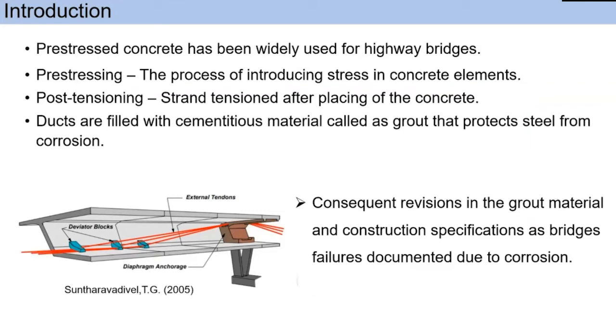This is a basic introduction. Pre-stressing is the process of introducing stress into a concrete element by tensioning high-strength reinforcing steel. There are two types of pre-stressing system: one is pre-tensioning and another one is post-tensioning. In post-tensioning systems, the strand is tensioned after placing of the concrete, and the remaining space in the ducts is filled with grout. Grout is a cementitious material which protects steel from corrosion, as the pore water of the grout has an alkaline pH which allows the steel to passivate.